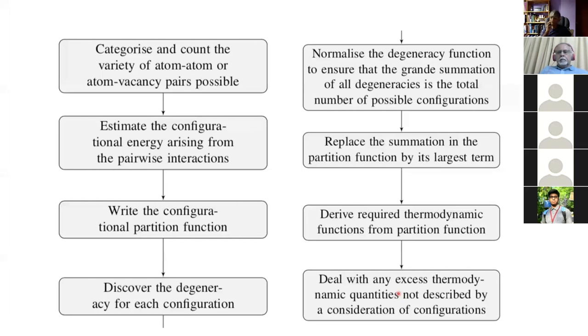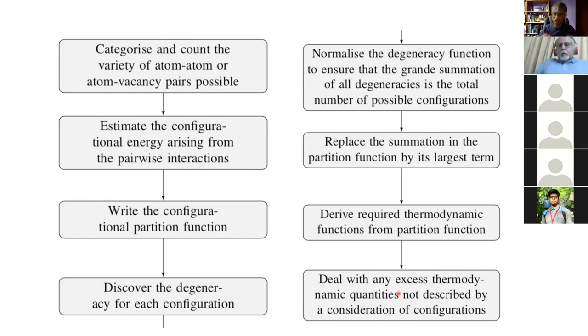Regarding high entropy alloys, which I mentioned in the very first lecture: it's remarkable that they all assume ideal entropy of mixing, whereas it is simply impossible in such alloy systems to actually achieve ideal entropy of mixing. Someone needs to do proper work to determine whether these are truly high entropy alloys, or whether the entropy is significantly lower because the atoms are not distributed at random.